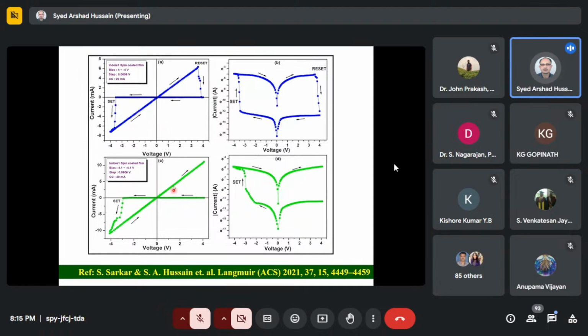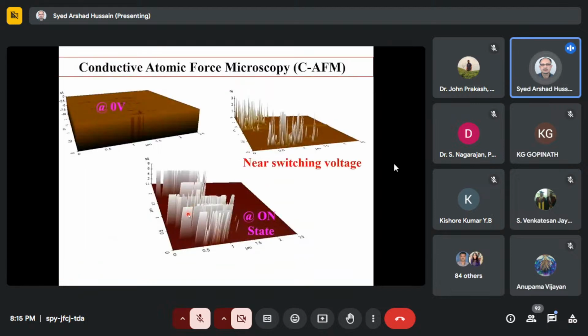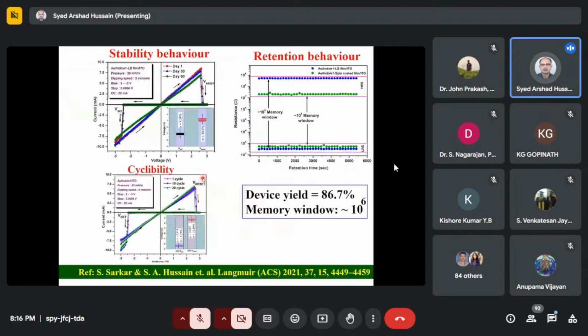And we have seen that when the current across the device crosses 20 milliampere, the device got short circuited due to Joule heating. Here you see, it cannot come back to its initial state. Okay. So this is the conducting AFM image of the device under different conditions. This is without bias. Near the switching, you can see the spikes due to conduction channels across the device. And this is after the on state, you can see that continuous channels are there.